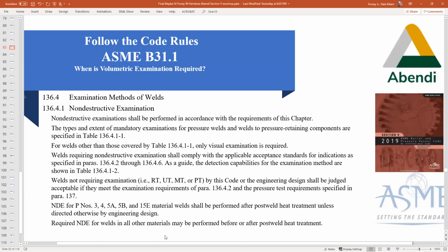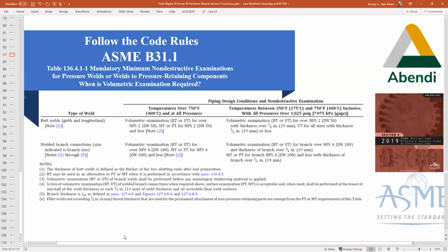That's 136.4.1-2. Welds not requiring examination, i.e. RT, UT, MT, and PT by this code or the engineering design, shall be judged acceptable if they meet the examination requirements of 136.2 and the pressure test requirements specified in paragraph 137. NDE for P numbers, and it lists different P numbers here, P3, 4, 5A, 5B, and 15E, material welds shall be performed after post-weld heat treatment unless directed otherwise by engineering design. And this is a good example where they're saying when the NDE is to be performed. Required NDE for welds in all other materials may be performed before or after post-weld heat treatment. Again, information of this nature is found within the construction code.